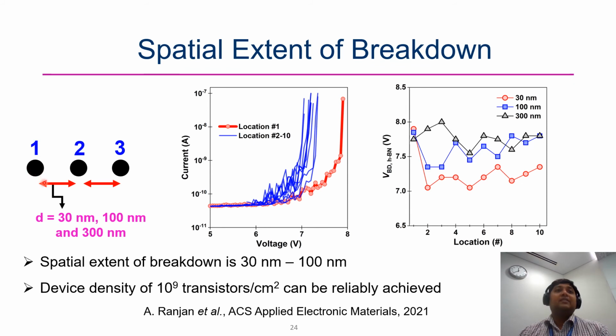We create a breakdown spot, and then we increase the distance, say 30 nanometer, and do another one, increase and do another one. In this way, we varied the distance. For example, we have 30 nanometer, 100 nanometer, and 300 nanometer. And the data for 30 nanometer is shown here.